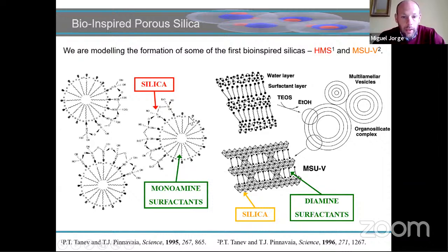So that's a key difference from the materials that I showed you before. The previous materials had ammonium surfactants, which means that the charge on the head group is permanent. So it's always positive, right? You cannot protonate or deprotonate the surfactant. With amine groups, on the other hand, you can, right? So we can change the charge level here at the head of the surfactant by changing the pH, okay?